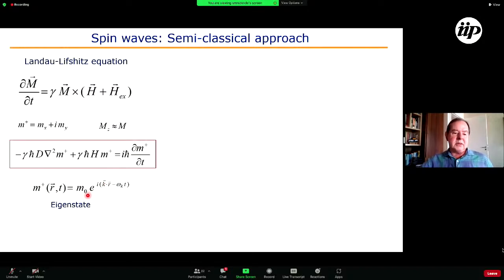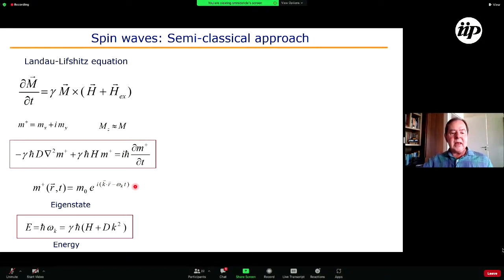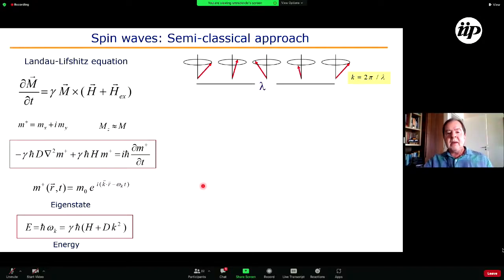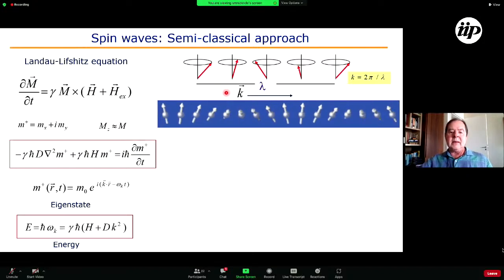With the solution of this equation, simply m0 e to the i (k dot r minus omega_k t), this is an eigenstate of the system, and the energy is proportional, as it says here. The energy varies with the square of the wave number, just like an electron in a flat potential. And the fact that we have used a variable mx plus i my means that there is a phase angle between my and mx. The solution is precisely a spin wave characterized by a frequency, which is the frequency of precession, and a wave number, which is 2 pi over lambda.